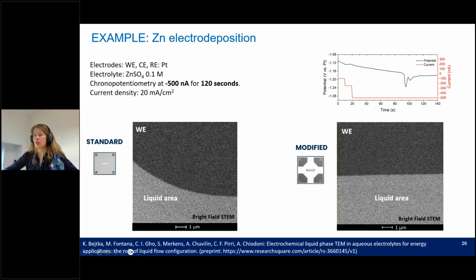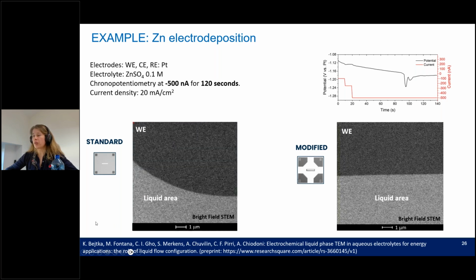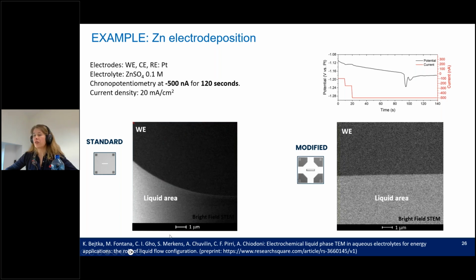And first, I show you here the experiment which was repeated on the basis of the Sasaki and co-workers experiment. So we ran the chronopotentiometry at the current density of 20 milliamps per centimeter square in the same electrolyte, and the cell has all 3 electrodes made of platinum. So when we close the cell with the standard slot sheet, we actually observe the same as was observed by Sasaki and co-workers. So immediately after the current is provided, the cell, actually this is not anymore liquid area, the cell is filled with the gaseous products.